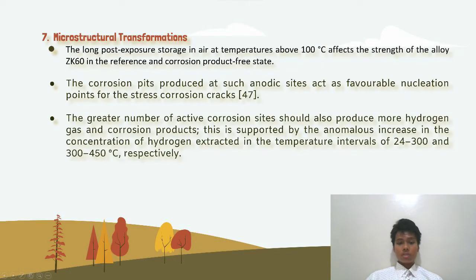7. Microstructural transformations. The long post-exposure storage in air at temperatures above 100 degrees Celsius affects the strength of the alloy ZK60 in the reference and corrosion product-free state. The corrosion pits produced at such anodic sites act as favorable nucleation points for the stress corrosion cracks. The greater number of active corrosion sites should also produce more hydrogen gas and corrosion products. This is supported by the anomalous increase in the concentration of hydrogen extracted in the temperature intervals of 24 until 300 degrees Celsius and 300 until 450 degrees Celsius, respectively.